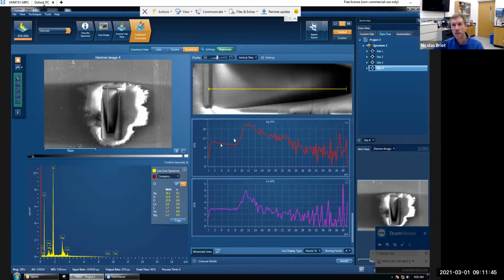What I was planning on doing today is, I have the two other samples that you gave me last week. Not the one embedded, but the glass rods that are fully exposed. I can see the surface. I was going to first do some EDS at the surface. So one of them is ion exchange in 100% potassium nitrate. And let's see in EDS if we can see the potassium and compare with XPS data. So I did XPS.